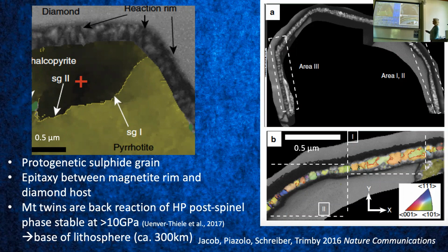Firstly, we could see that this large inclusion with the rim is in fact a pyrrhotite. This pyrrhotite is protogenetic because it showed deformation. The diamond was not deformed, the inclusion was deformed. You cannot deform one without the other if it had been included, so this deformation had to have happened beforehand. So this sulfide was not formed with the diamond, but was randomly included by the diamond after it had already been formed. So it has a prehistory. That was an interesting finding.